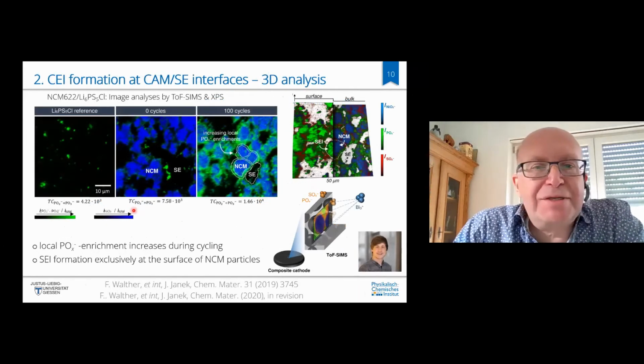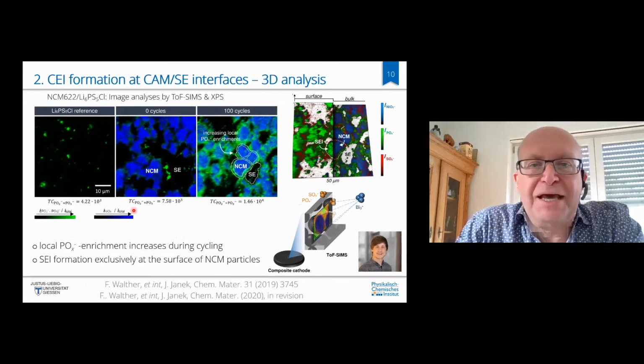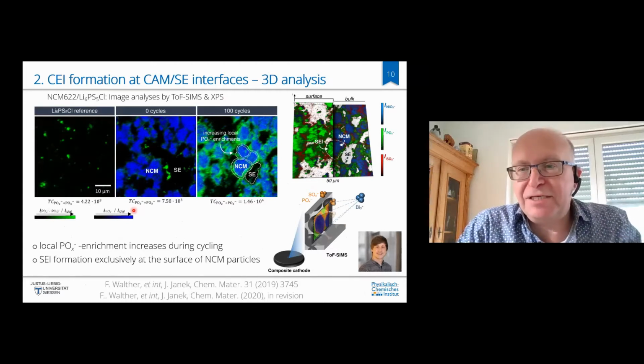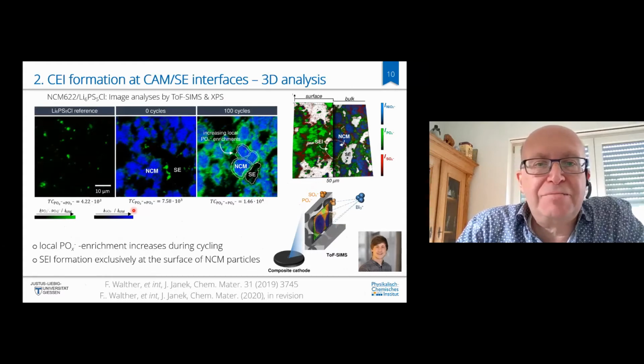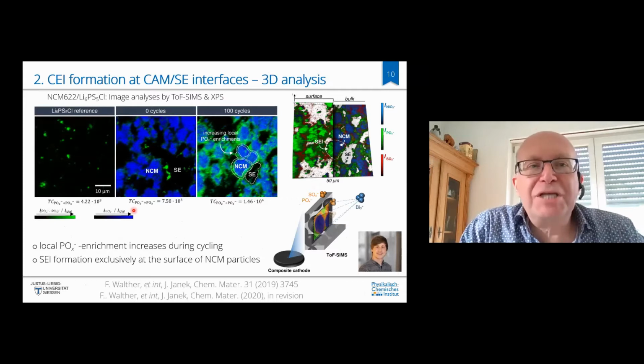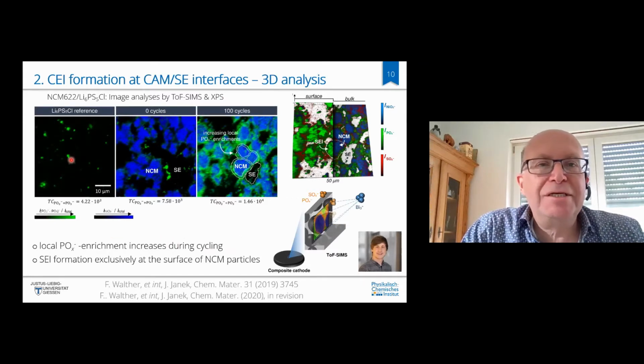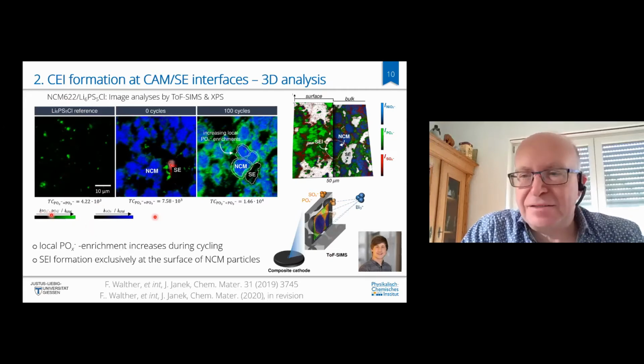Okay, now an issue is, of course, that if we use these sulfides and thiophosphates, they have a narrow stability range because they're easily oxidized. They contain sulfur in the oxidation state -2, and that is easily oxidized already at potentials of, let's say, 2.3, 2.5 volts. So always when they are in direct contact with cathode materials, which of course always have a higher potential, they degrade. And what you see here are ToF-SIMS images where the color corresponds to certain species. So this is a mass spectrometric image, and you can also get it in 3D. What you see here is the argyrodite in the cathode composite, pristine after 0 cycles. The blue color is representing the nickel, the NCM material, and the green color is representative for phosphate. Now, a thiophosphate does not contain oxophosphate, but you see, after 100 cycles, there's lots of green color around the blue cathode particles.